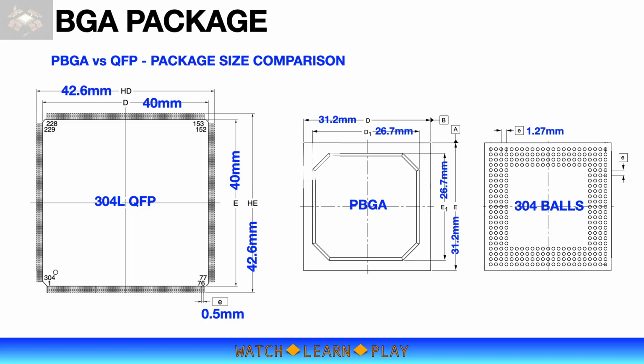Here's a quick comparison in package size between the 304 leads quad flat package or QFP versus 304 solder balls BGA package. The 304 leads QFP package has a body size of 40 by 40 mm and a footprint of over 42 by 42 mm with the leads. In comparison, a BGA package with 304 solder balls is only just over 26 by 26 mm in body size and footprint of about 31 by 31 mm. That is about 46% reduction in board space.